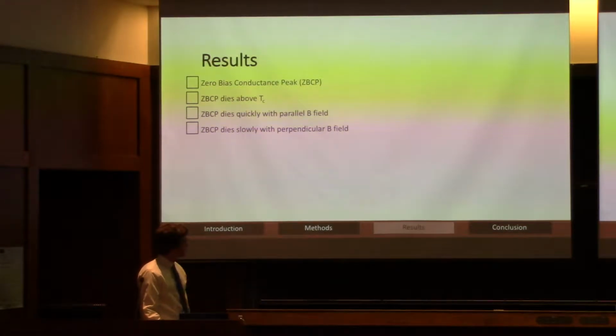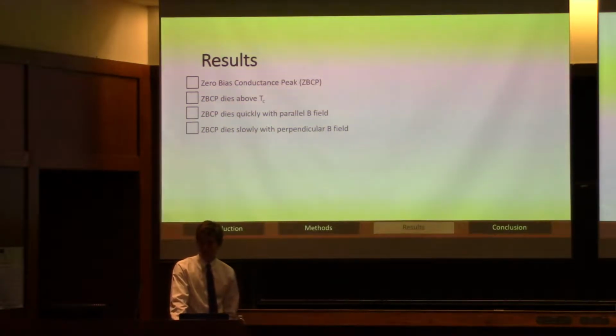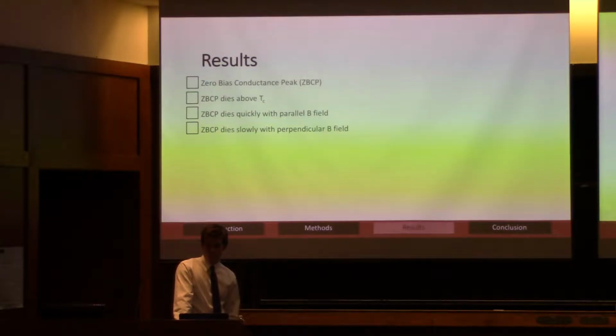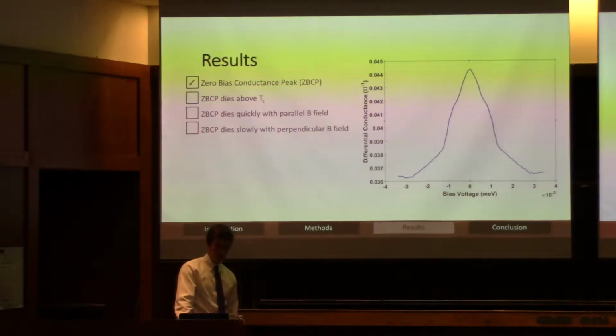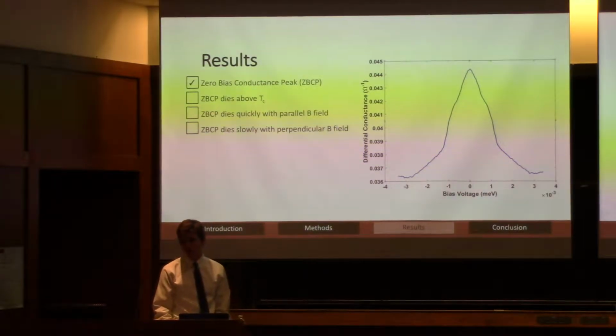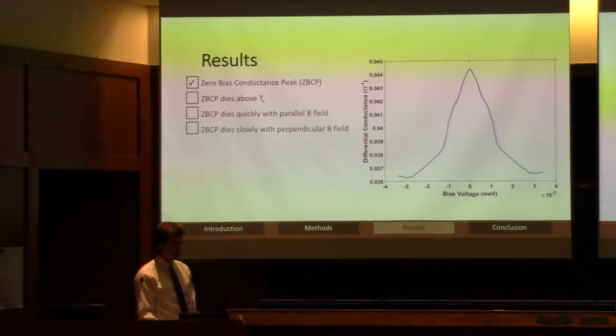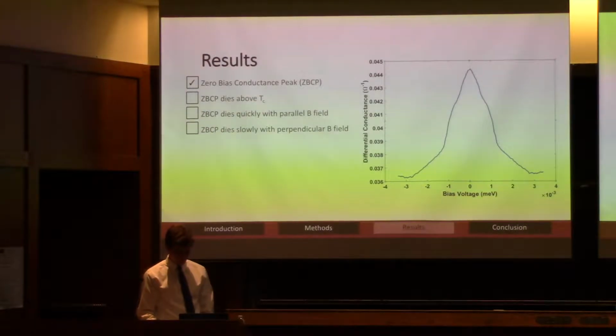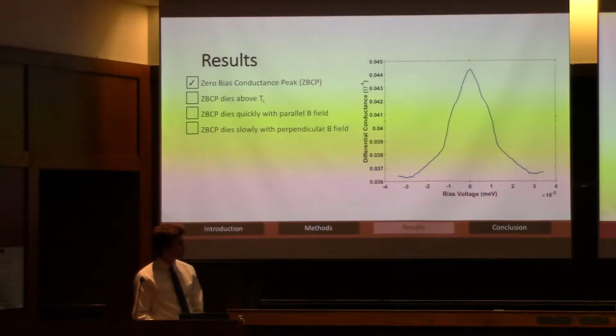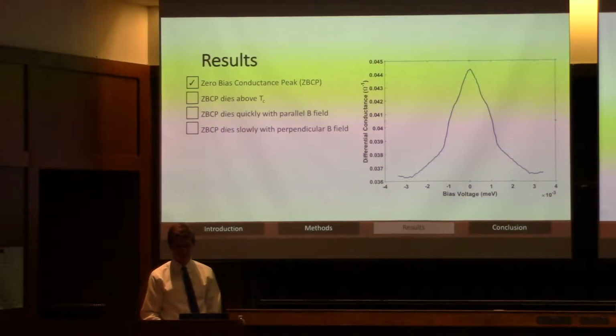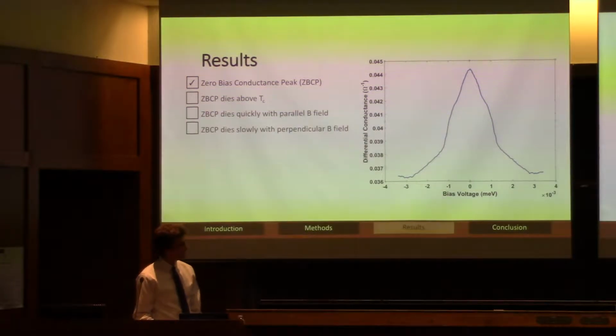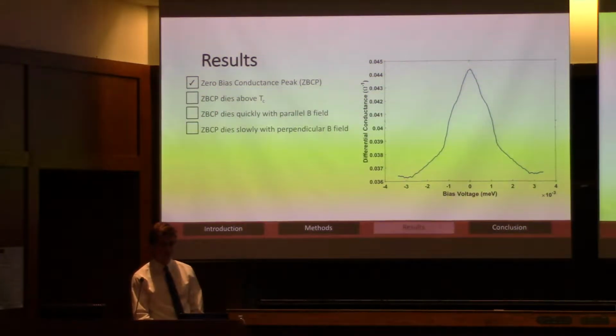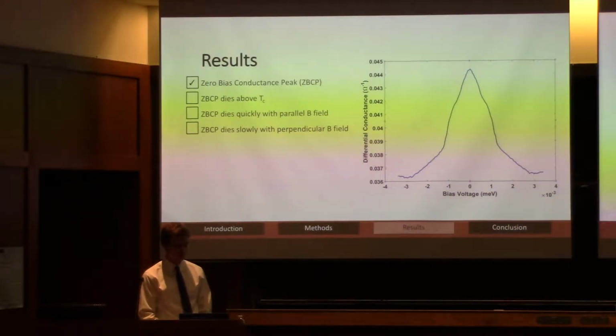So, our results. Again, we were looking for that zero bias peak that shows that new phase of matter, and in fact, we did see that. So here's that graph again. At 0 voltage, you get a peak in conductance, and that has to do with how those holes are reflected in Andreev reflection. When you get constructive interference in those holes, you get that peak, and when you get destructive, you get these shoulders coming off the side, and then as you increase your voltage, you start to return to more of a normal metal-type behavior.